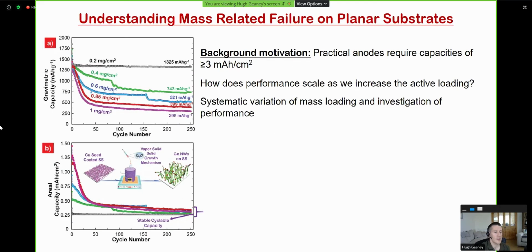Again, as Michal said, when I came back to UL, I was tasked with trying to scale up these materials for an Enterprise Ireland project. What I found with the initial substrates that we had previously used, stainless steel, for growth, was that as we increased the mass loading on this stainless steel, the performance started to suffer. This is a well-known issue, but it's actually not shown in the literature very often. It's one of these hidden hurdles that people may not necessarily address and really deserves attention.